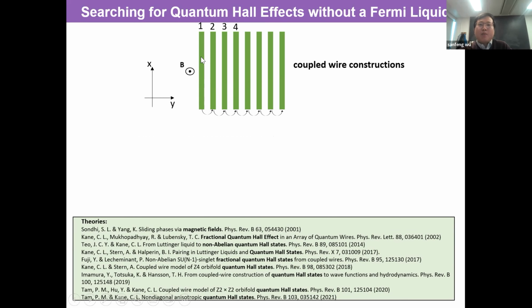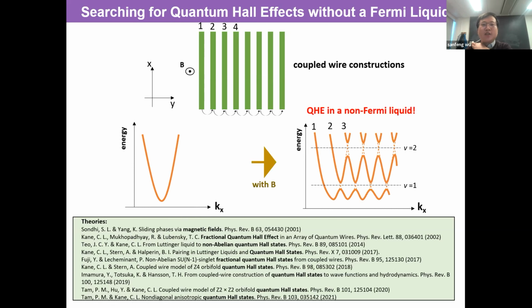So if you have coupled Luttinger liquids, a lot of theory papers are listed here, many of them actually from Kane, C.L.. So you think about applying field to the coupled wire system. If you have zero field, each wire in the simplest setting is just one parabola. So if you apply magnetic field, you're going to introduce a vector potential A, which will shift the momentum of each wire's parabola. And you're going to shift them differently for different wires because they have different distances to the first wire, right? So you get something like this. And then you turn on interaction between wires. You actually can open a gap.